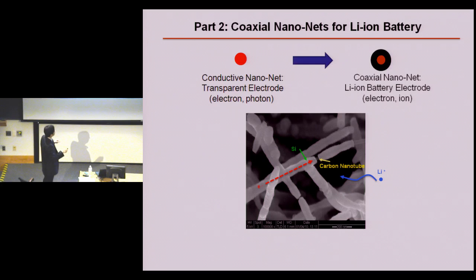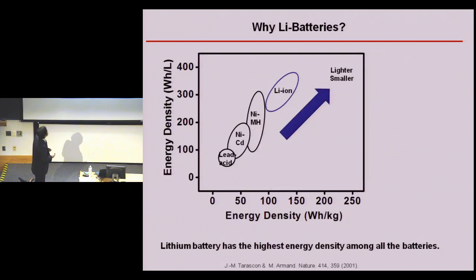And because of this porous structure, lithium ions can transport very effectively across the entire structure, so that it will effectively decrease the diffusion length for the lithium transport into the silicon. So I'm going to show you how this kind of core-shell structure can function very effectively as a lithium-ion battery anode. The reason why the lithium-ion battery is so attractive to many people is because it has a very high energy density per weight and also very high energy density per volume compared with other kinds of battery devices.